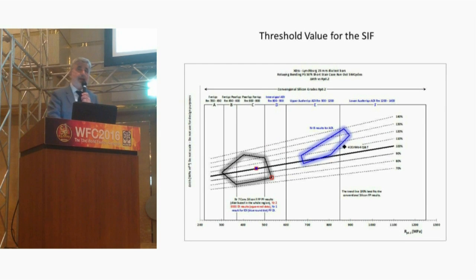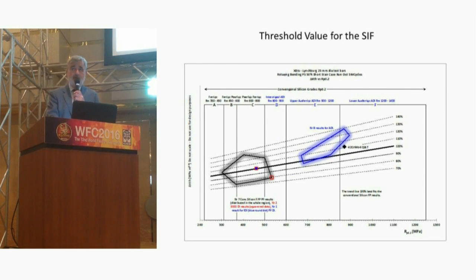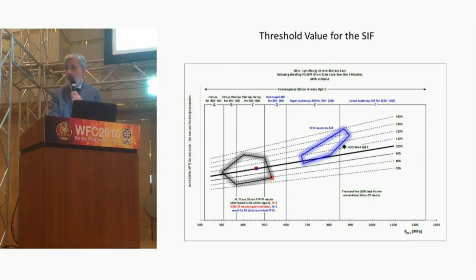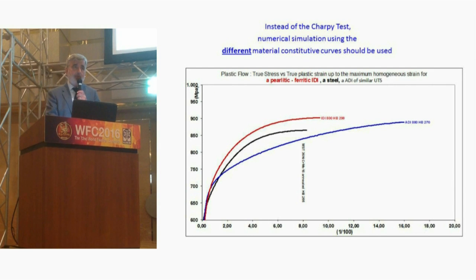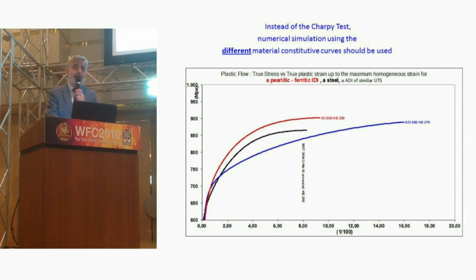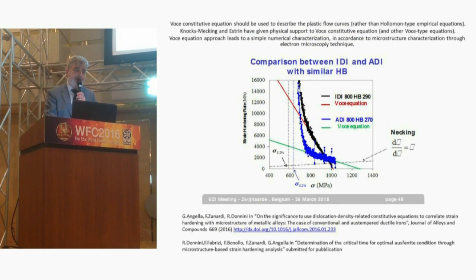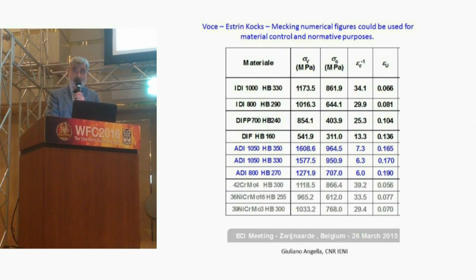same material. And you see that we always make the same test with a 42CrMo4 quenched and tempered steel, to be sure that the same procedure is also applied to the comparison steel. Instead of the Charpy test, we propose that a constitutive curve be used, because this will be much better for the component itself when we are testing at high plastic deformation. These curves can be described by the Voce approach that we are using now at our company in order to give a numerical value to the shape of curves, also for process control.